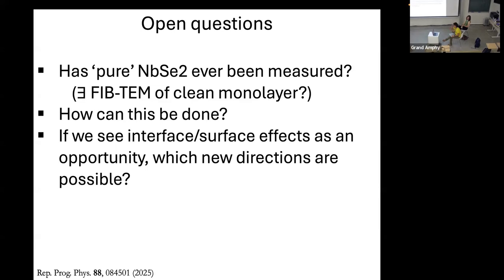Unfortunately, Mathieu has done some suspended devices with the goal of gating from the bottom. In fact, I think he has one of the papers where he was gating, because there was a criticism of his earlier experiment that is gating from one side. So he actually did a follow-up where he was gating from 2 sides. The way to gate from 2 sides is that you make a trench and then you flood the trench with his ionic liquid. So it's a pity he's not here. We discussed this extensively a couple of years ago when he was visiting, and it's very doable.